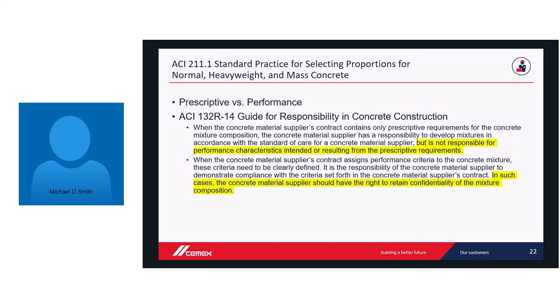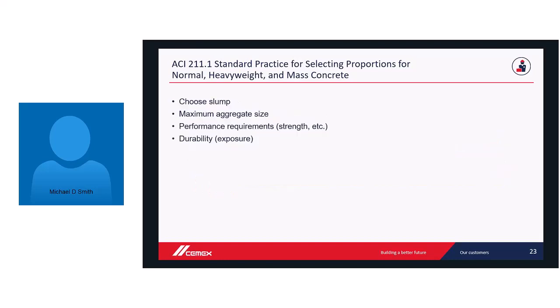I think many years ago we managed to convince LA County or LA City to accept a mix that just stated certain standards, basically like a certificate of compliance. The mix stated that it complied with this, that, and the other thing standard for cement, for SCMs, for aggregates, but it didn't spell out any actual weights or any specifics of the mix design itself. We were responsible for the performance. They accepted the mix as it was, but it didn't have any specifics of the design itself. So it can be done. It's difficult in a lot of cases, but you do have some rights to confidentiality of your mix design, especially if you're doing a lot of research and development and putting a lot of effort into those designs.